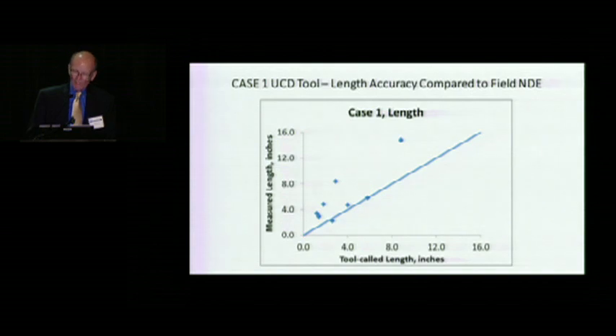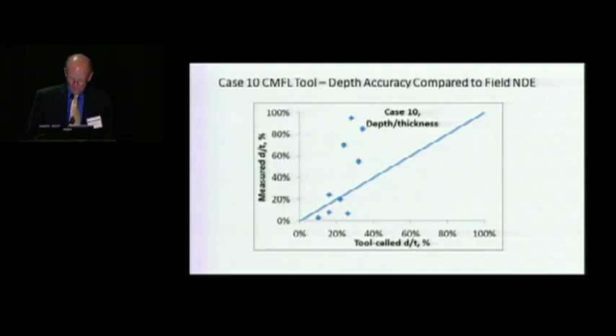As far as length accuracy, usually the tools are a little better on length accuracy, and as far as measuring the length in the field, you don't have to do that usually. If they're OD cracks, and a lot of these were, you can use magnetic particles, and you get a pretty good correlation between length and tool calls in that case.